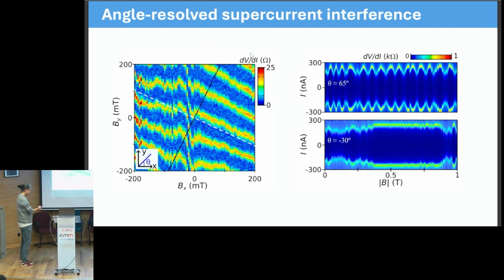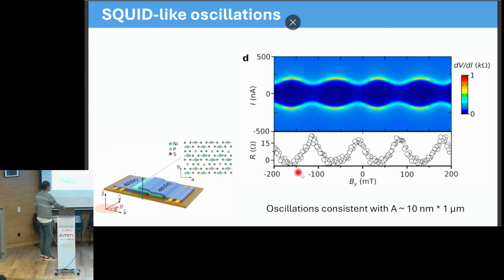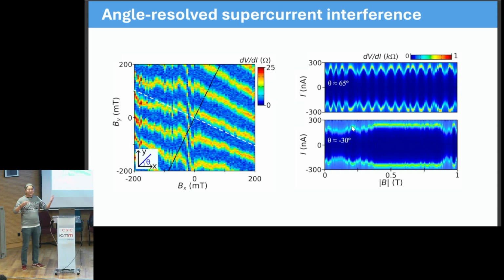Just to explain, what I'm plotting here is the zero bias resistance, which is what I plot over here of the same measurement. As you can see, when the supercurrent goes to the lowest value, then we see a peak in the resistance, because the supercurrent is low compared to temperature, so we see a small resistance over there. So following these peaks, we can follow how the oscillations vary as a function of the angle of the field. And essentially this is telling us that we indeed have two localized states. When the magnetic field is completely perpendicular to this plane, it is essentially perpendicular to these diagonal lines. And when we're parallel to the diagonal lines, it would be like applying the magnetic field and not really threading the area between the two loops, because they form a line. And indeed, when we take a measurement along these lines, we don't see oscillations. Okay? So it seems that we have truly two localized states.